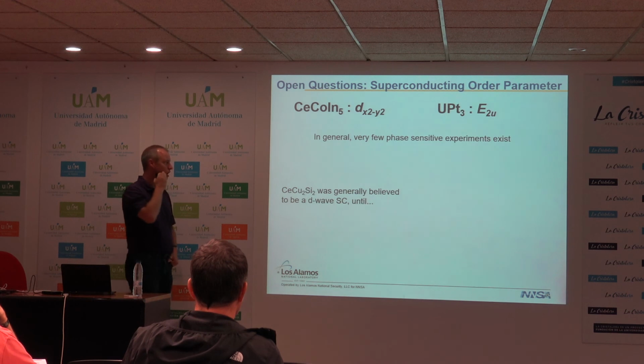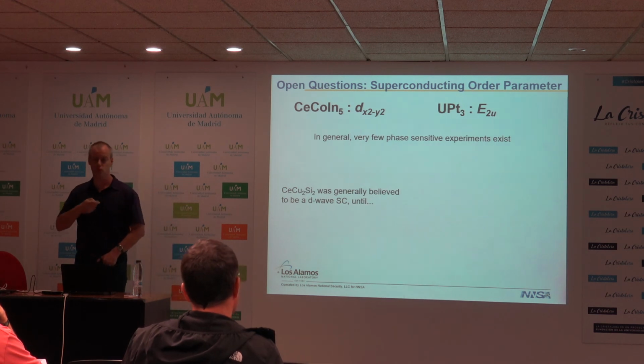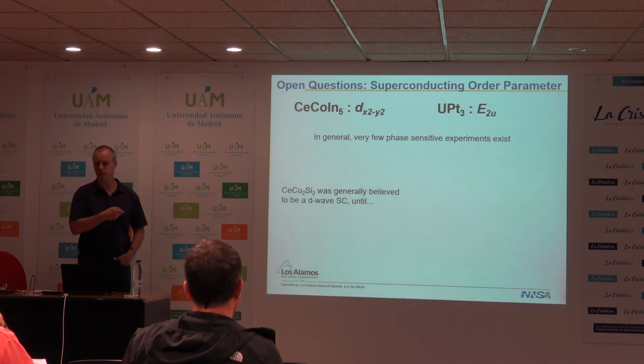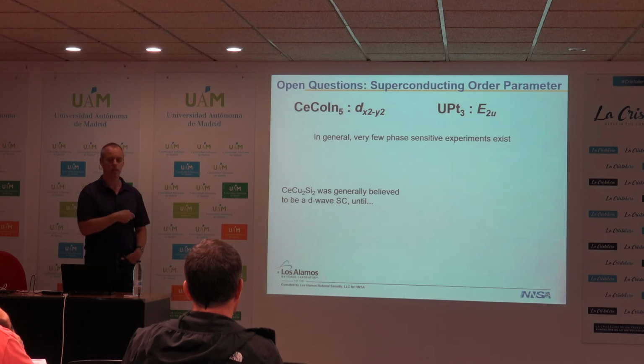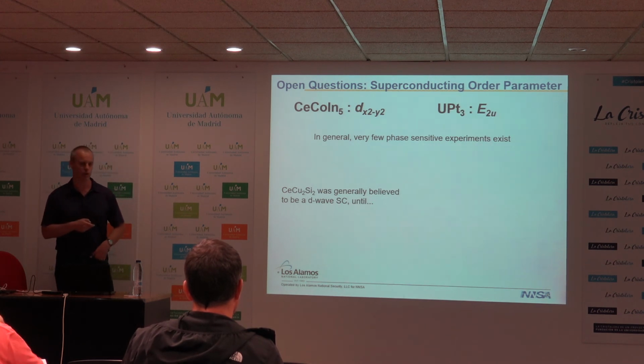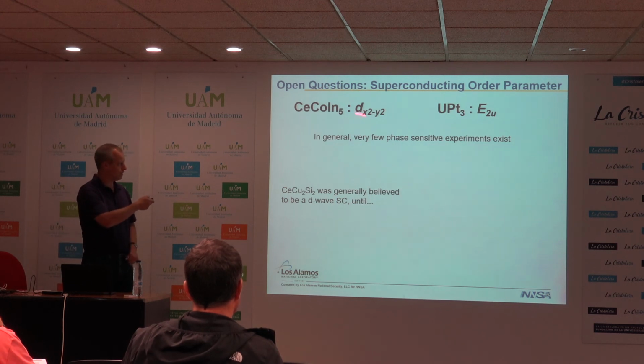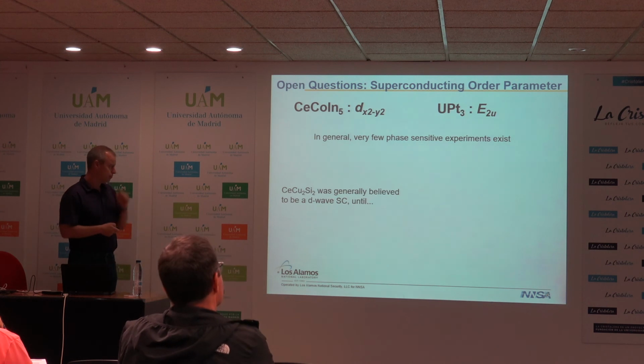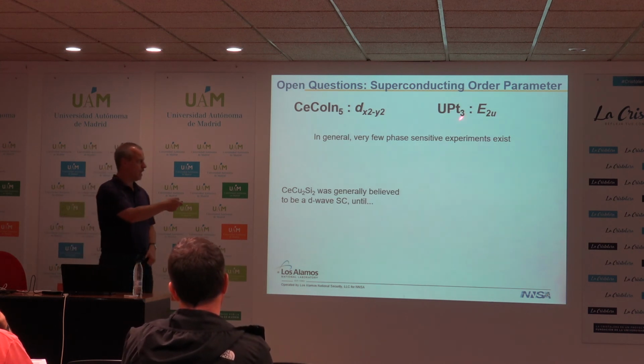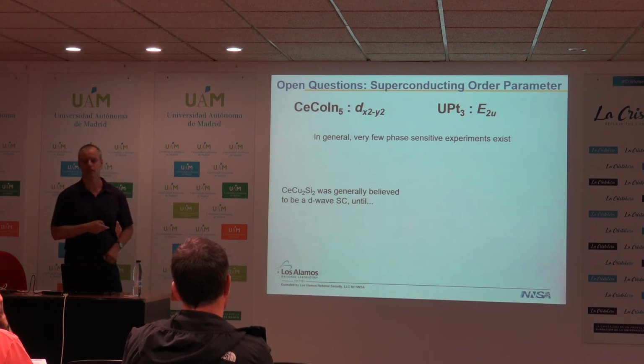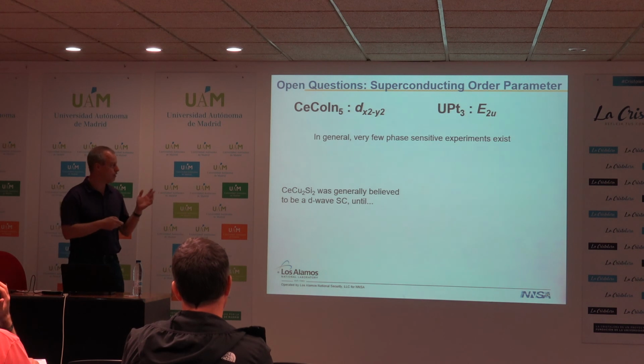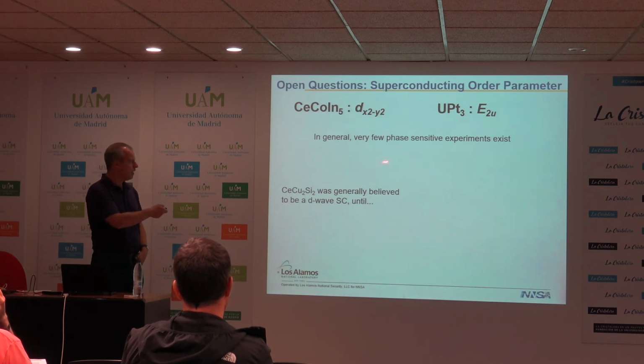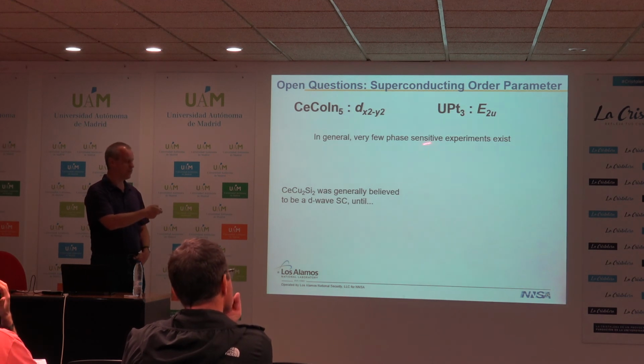Okay, open questions. I'd be remiss not to mention that for the superconducting order parameter, I showed a huge variety of different compounds, but there are only really two where it's relatively well established what the superconducting order parameter is, and that's CeCoIn5, which is pretty compellingly a d_{x²−y²} order parameter. There are even a few phase-sensitive experiments. And UPt3, which is believed to be a spin triplet superconductor, has an E2u representation for the order parameter to be able to explain the 3 different superconducting phases. But if I could make a plea, in general, there are very few phase-sensitive experiments on heavy fermion superconductors.